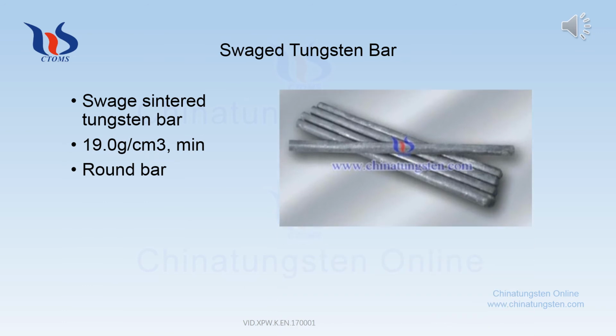Swaged tungsten bar is swaged from the sintered bar. After swaging, the density will be increased to about 19.0 grams per cubic centimeter.